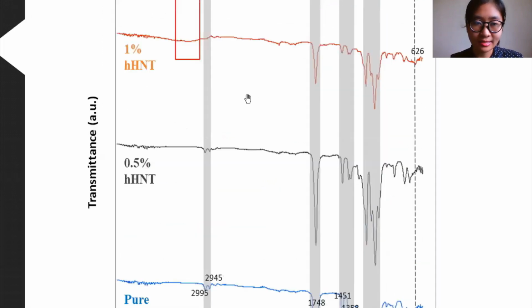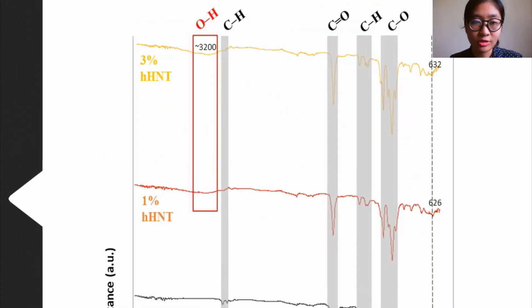At increasing clay content, a broad signal was observed at around 3200, which indicates the presence of oxygen-hydrogen bonding. This in turn has affected the signal of the carbonyl bond stretch for PLA. The intensity of the carbon-oxygen double bond was observed to decrease at 1% HHNT and 3% HHNT, which may indicate a weakening of the dipole moment due to formation of OH bonding.